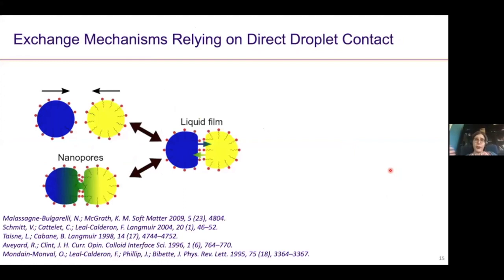So what we know so far, and I'm going to conclude quickly, is that the micelle systems are not really dominating the transport of oil. And so we believe that the transport is actually similar to what Professor Cabane had suggested, and that is that droplets have to collide with each other and then exchange oil when they're close to each other. So they don't coalesce, though, because we don't see any significant size changes as a function of time, but they collide for an appreciable amount of time. And this is enough to allow for exchange of oil between droplets.